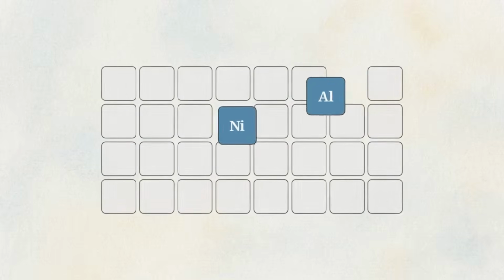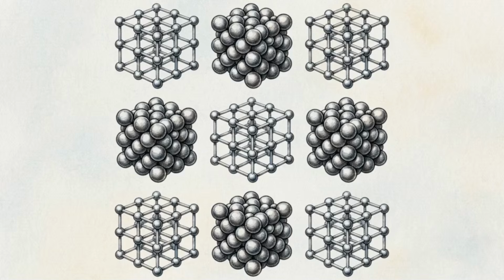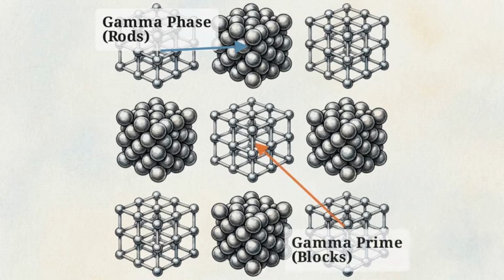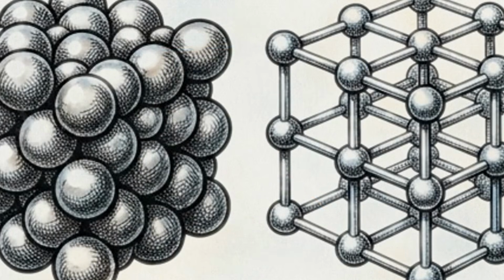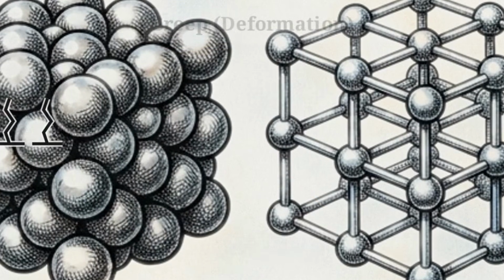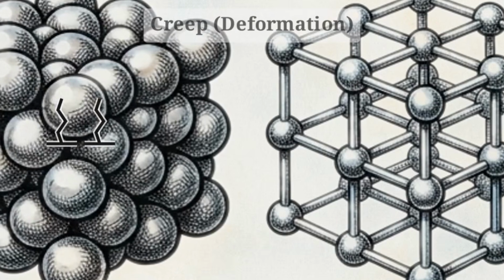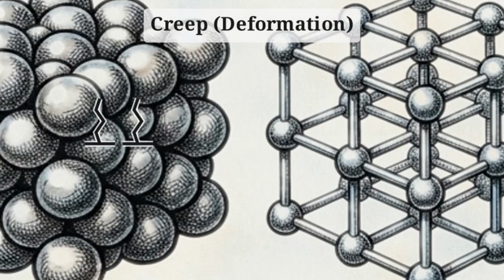By carefully mixing in specific elements like aluminum, they redesigned the metal itself at the microscopic level. When you zoom in, the microstructure looks like a chaotic city grid. You have regions where the atoms are randomly placed, forming these rod-like shapes, intersecting perfectly with repeating, ordered cubes of atoms called blocks.